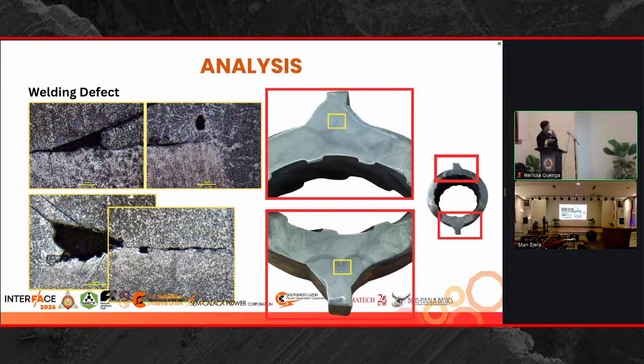As we can see, the crack tips here are oxide filled, so that is how we confirm that this is from the welding process itself and it's not surface induced. Still, these points can act as stress concentrators. So that's why we are also very concerned with observing these types of defects, especially for welded components that are statistically very prone to failure compared to the base metal.